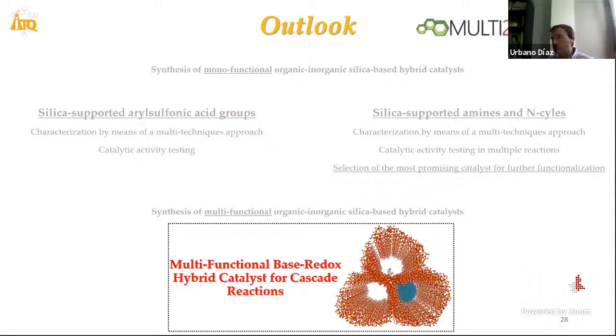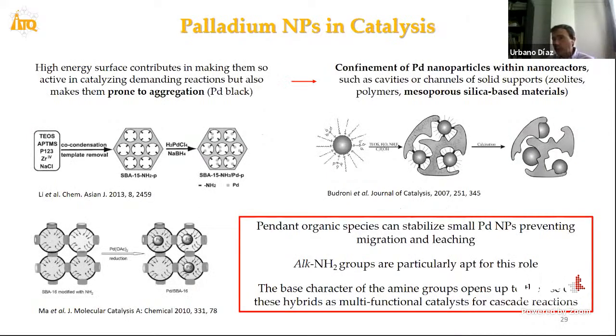The third type of family obtained from this type of single site catalysts makes it possible to obtain bifunctional hybrid catalysts, in this case by the incorporation of redox active sites in the architecture on the surface of the silicon matrix. Now the high energy surface contributes to making them so active in catalysis of demanding reactions, but also favors the aggregation of the metallic nanoparticles on the surface of the porous materials.